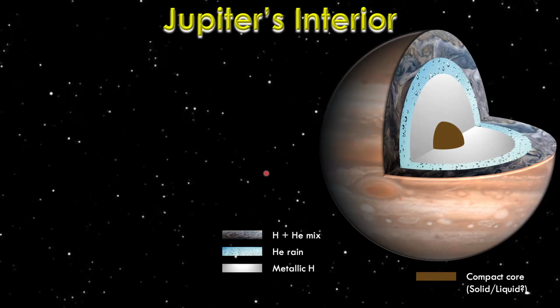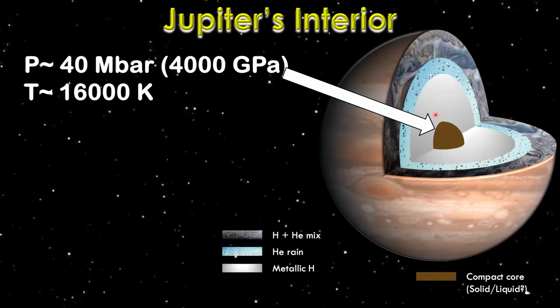So after the planet was formed, there was a lot of chemistry that went around, and it left an upper layer of hydrogen-helium mixture, and below this one is a layer of helium rain, and only below those layers, there's a region of an ocean, actually, of metallic hydrogen, which is actually what makes the entire magnetic field of Jupiter. But since this metallic hydrogen was formed later in the formation of Jupiter, then is it possible that at the conditions that this core is now, which is about 40 megabar, and temperatures of thousands of Kelvin, the metallic hydrogen can dissolve the core, right? So how do we even address this if we don't have any experiments that can even synthesize metallic hydrogen and play around with rocks? We have to do chemistry from first principles.